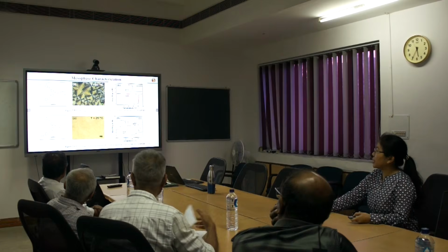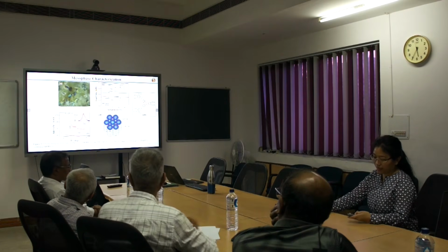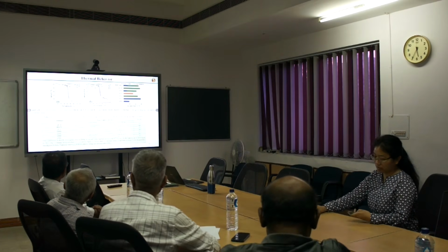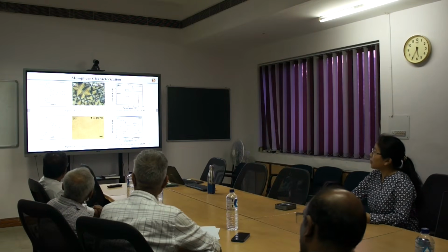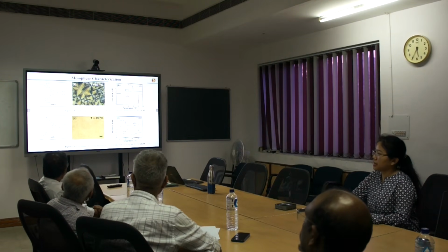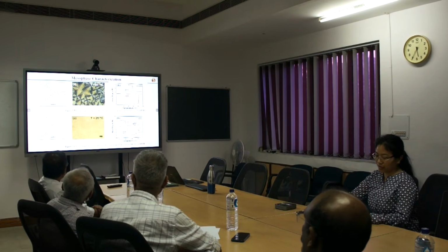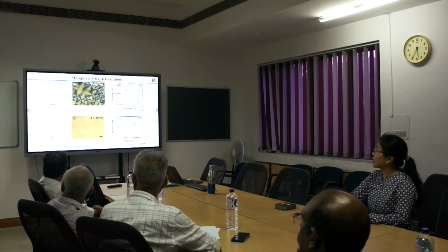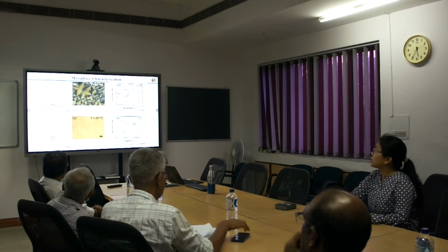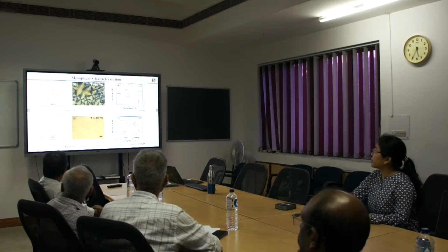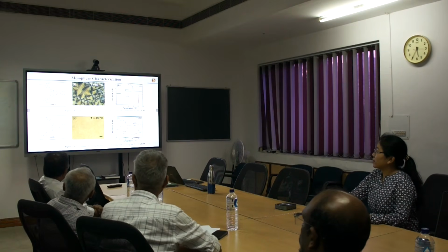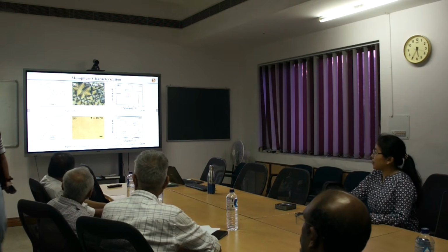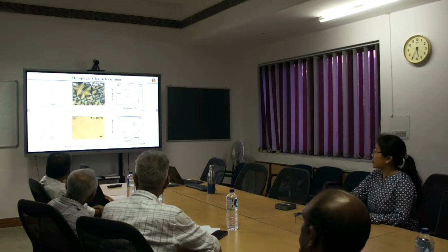But for QER3, two alkoxy chains are present at this position. Under the polarized optical microscope, it had a crystalline texture, which was evident from the DSC curve as well. And for QER4, it had only a methoxy chain at this position, and it formed this type of texture, and DSC suggested that it could be because of slow crystallization.